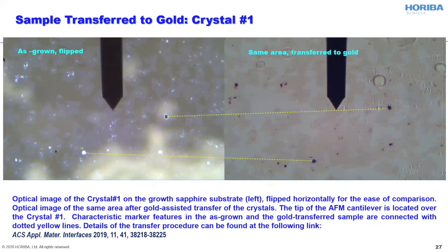So the good news was that we were able to find exactly the same flake that we characterized before with conventional confocal microscopy. And as you can see, here is this very specific formation. We can see it here in the transferred sample, and the crystal that we analyzed before the transfer is exactly the crystal that we analyzed after the transfer to gold.